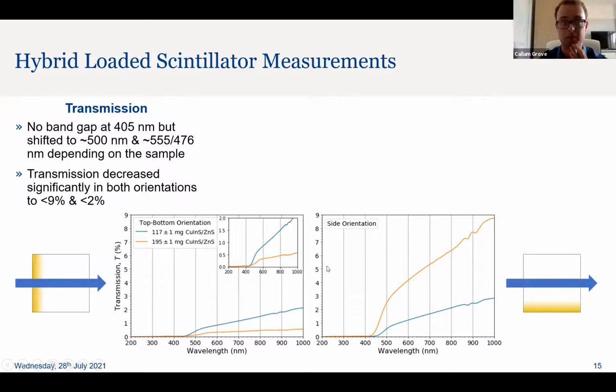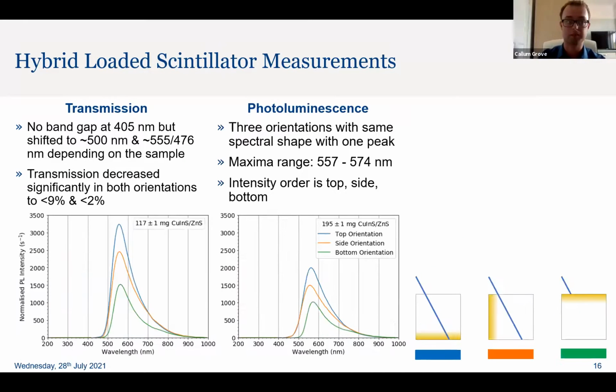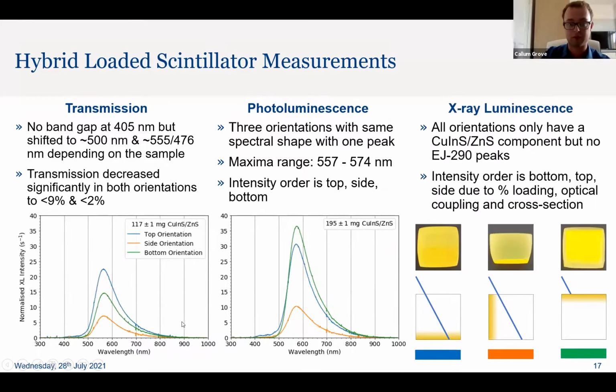Yeah. So the similar story for the hybrid loading. We have a drop in intensity for the transmission, significantly to less than 10%, less than 2%, depending on the orientation. And this is because of the highly loaded and opaque regions in both the bulk and sedimented layers. In photoluminescence, there's hardly any plastic emission, and it's all quantum dot emission, suggesting that all of the plastic emission is being absorbed by the quantum dots and emitted at the 550 nanometer range.